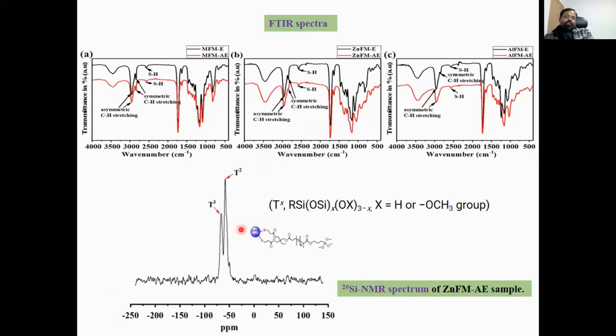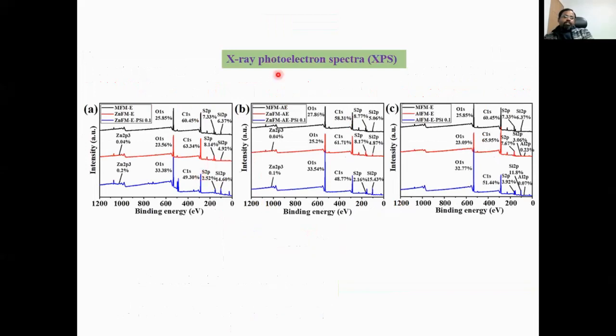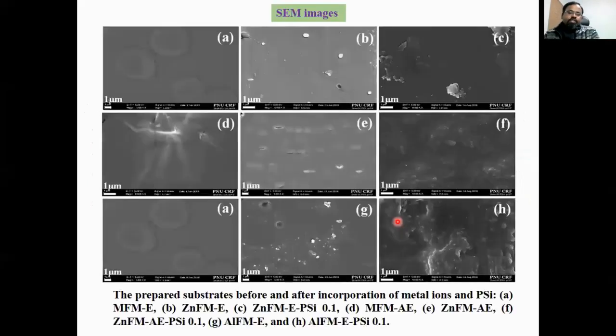And we also checked the silicon NMR of these synthesized materials. It shows the alkoxy functional group is still maintained on this coated substrate after reacting with the methacrylate silane precursors. And further, we checked the chemical compositions by XPS. To confirm zinc as well as aluminium present in the coated substrate, we used X-ray photoelectron spectroscopy. It shows we can confirm the presence of other elements like carbon, oxygen, sulfur, and silicon in the coated materials. So we confirmed this, and further we check the morphology of the coated substrate on the glass substrate.